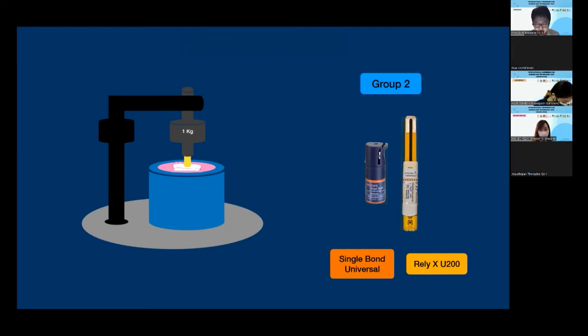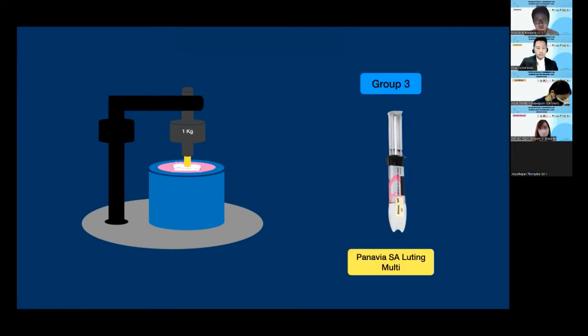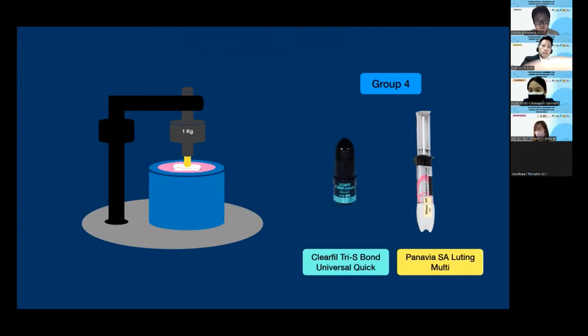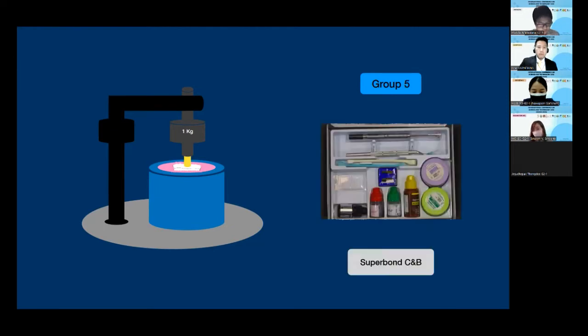A Single Bond Universal adhesive was applied on the dentin with a micro brush in a self-etch mode according to the manufacturer, and then followed the protocol of group 1. For group 3, we changed the cement to Panavia SA Luting Multi and used the manufacturer's recommendation. For group 4, we combined the Clearfil Tri-S Bond Universal Quick with Panavia SA Luting Multi. The steps were quite similar to group 2. For group 5, we used Super-Bond C&B.